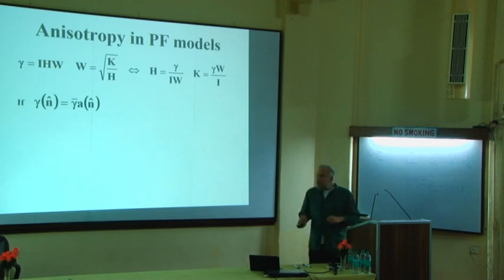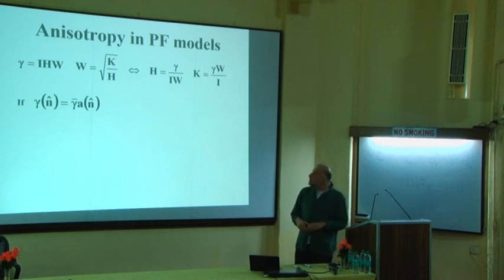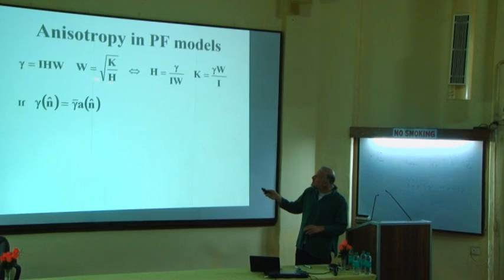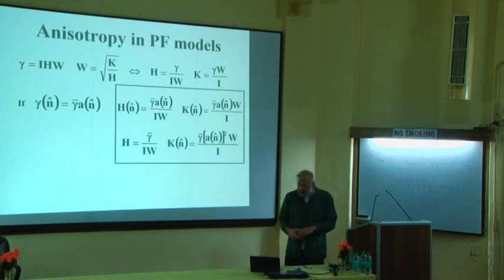So now, if I want to make the surface tension dependent on orientation, so I write this as gamma bar times an anisotropy function A of n. N is the unit normal vector. Well, how can I do that? Well, you know, see, I have an expression of gamma, and it depends on the coefficients of my phase field model. So I can invert this sort of.